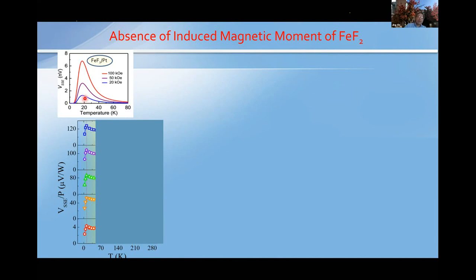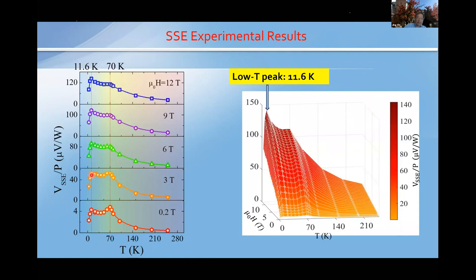Okay, so the reason I cannot show these peaks alone is because, if I go back, these two peaks are relatively broad, especially the high temperature peak. So I cannot reliably separate these two peaks. Otherwise, you can view these two peaks superimposed on top of each other, right?